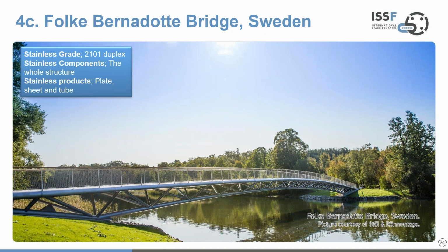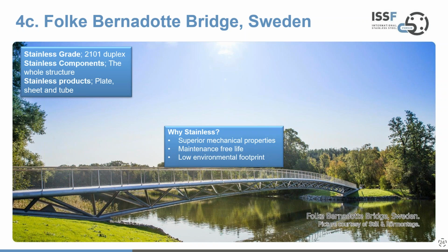I'd now like to switch to Sweden, to a very attractive bridge, the Folke Bernadotte bridge, which was made completely out of 2101 lean duplex. So the whole structure here is made from stainless steel. And this is a combination of hot rolled plate, cold rolled sheet, and tubular products. And the reason stainless steels were chosen here was the superior mechanical properties, again, of the duplex family of grades, the need for a maintenance-free life, and the low environmental footprint. And this is quite an attractive bridge, which provides a nice link over the water, and this shows one of the sort of design appeal features that stainless can bring to bridge construction.